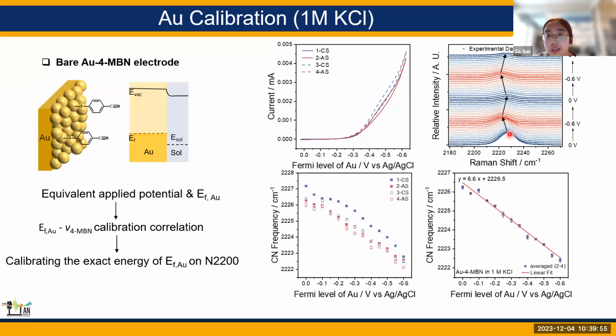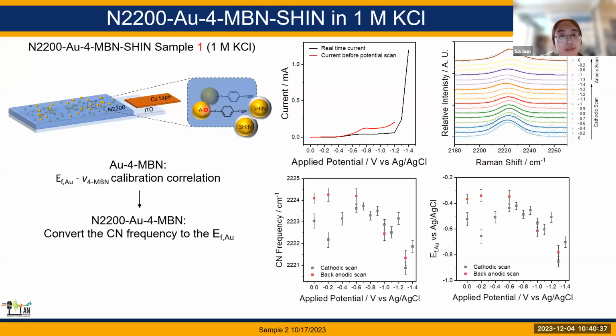And we can see that from the first cathodic scan, the nitrile frequency has a red shift, and then in the following anodic scan there is a blue shift back, and it's pretty repetitive. And then after fitting, we can summarize the CN frequency change as a function of potential, and it shows like this. After averaging, we can get the frequency of nitrile as a function of Fermi level of gold. So basically it's indicated by this equation. And with that, we can move to characterize the Fermi level of gold over here on the N2200.